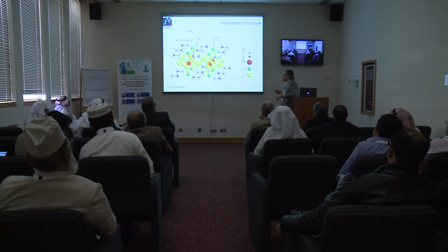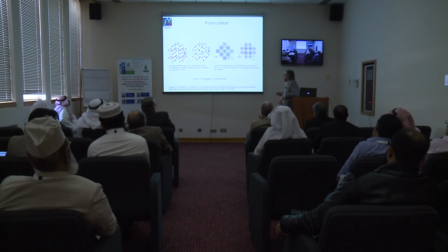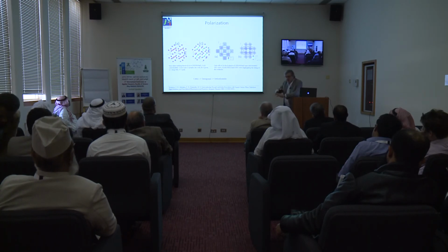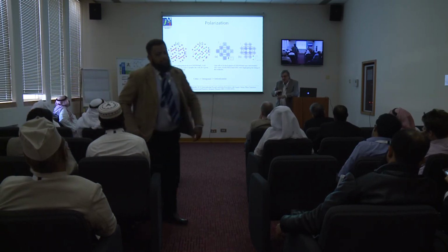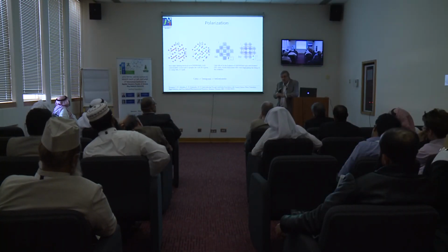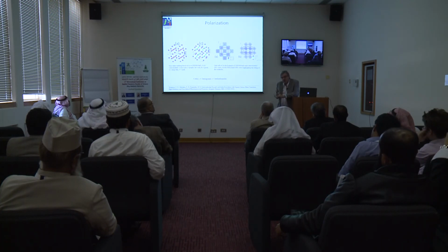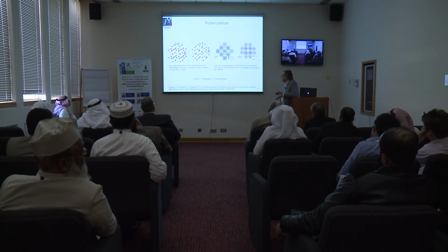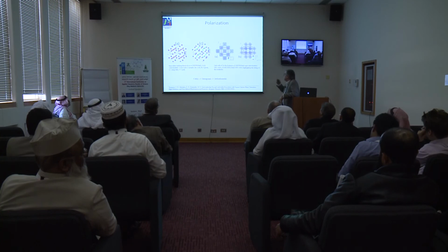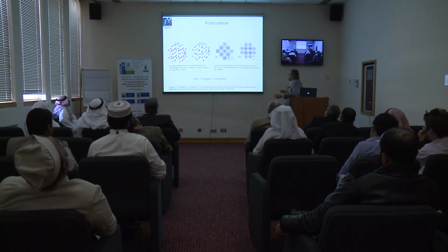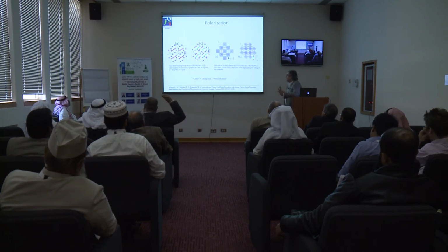So it's an organic, inorganic, and very soft structure. This is something we need to learn to control. Okay, so here, for example, is another possibility of distortion. When these things become favored at a certain temperature, this will change structure. So you have some phase transition. At room temperature, you have one from cubic to tetragonal, and then you don't have any more symmetry. And at 150 Kelvin, more or less, you have another phase transition still. So this is a structure that can be transformed in many ways.